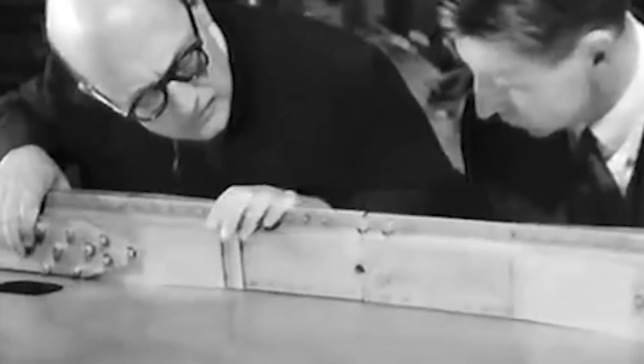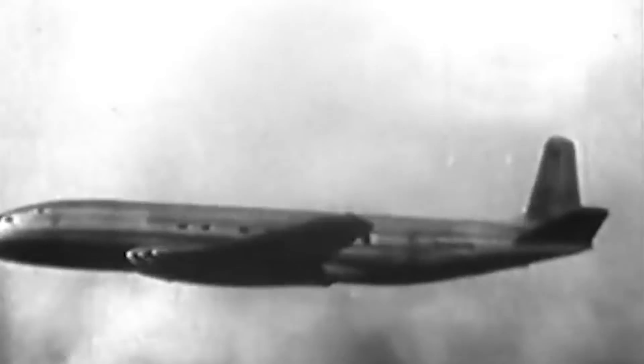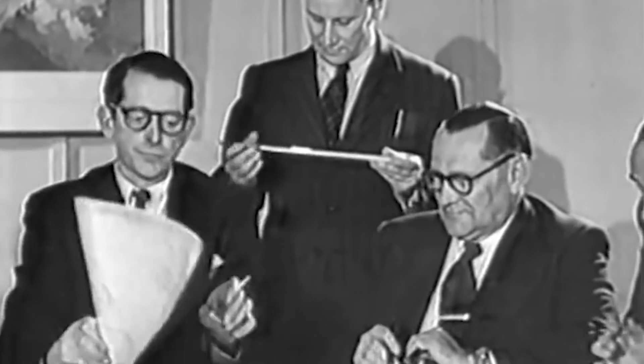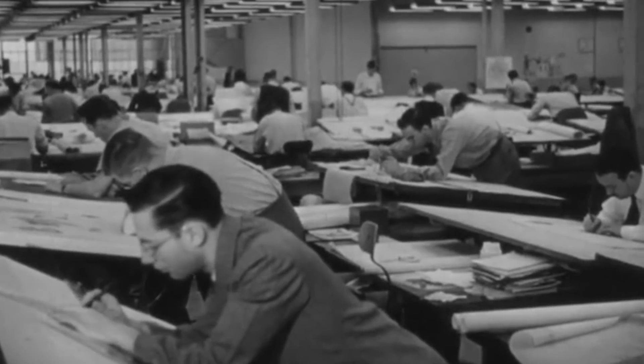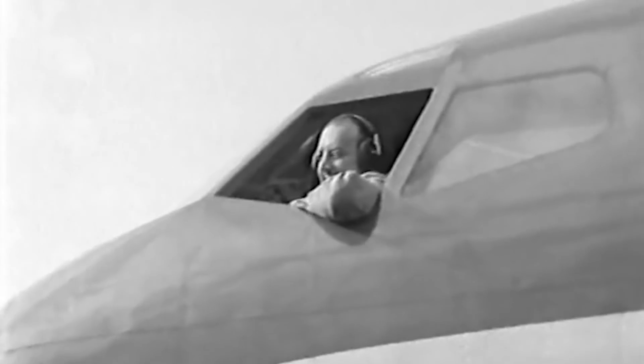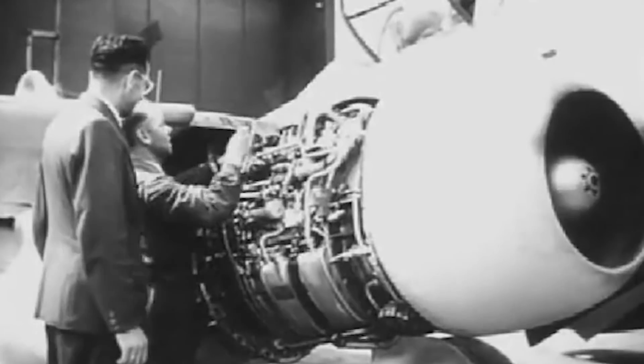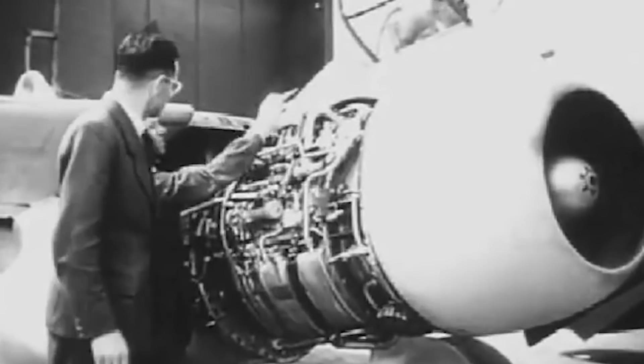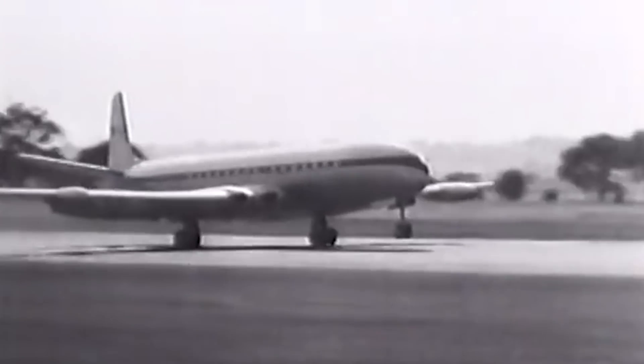Analysts concluded that each time the Comet took off, cabin pressurization made the metal around the windows and the airframe expand slightly. After landing, the metal contracted again. As the aircraft performed more flights, the metal weakened to the point that it could no longer resist most pressure. Metal fatigue was the cause behind the overall malfunctions. De Havilland would extensively modify the Comet for years after that, but it lost its market dominance. Airlines discontinued the use of Comets and relied on American aircraft such as the Boeing 707 or Douglas DC-8. It's said that engineers from these American manufacturers used the Comet's experience to adjust their designs accordingly, avoiding any accidents of their own.